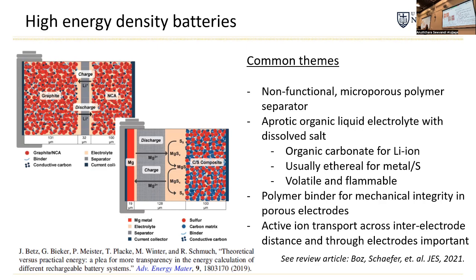So really the function of the polymer there is just so that the electrodes don't actually touch, but there's holes in it, and then we fill in those pores with an aprotic organic electrolyte. And so for lithium-ion systems, this is an organic carbonate mixture that you then dissolve salts in. But for any type of metal sulfur cell, we're usually using ether type mixtures. So the solvents are different. They have different properties, but they're all relatively volatile with higher vapor pressures, and they're flammable.